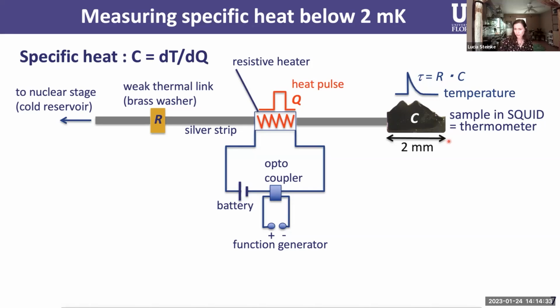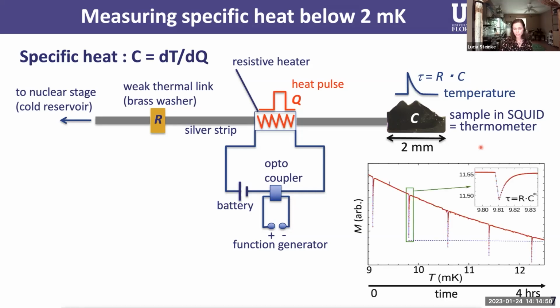In this case, our workaround was to use the sample itself, because we knew that the sample had a very strongly temperature dependent magnetization, and we still had it inside our SQUID magnetometer. So we decided to just look at the magnetic response of the sample. And that's what that looked like when you measured it. So what you see here is magnetization versus temperature, which is slowly varying over time because we apply constant heat to our cold reservoir of the nuclear stage.